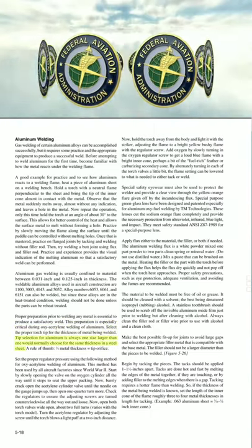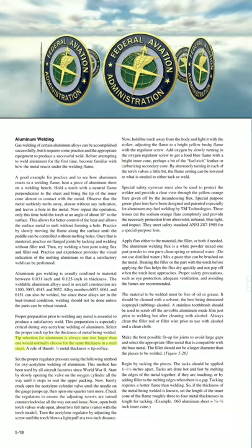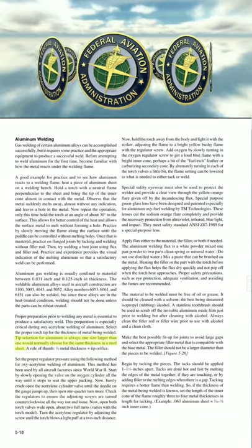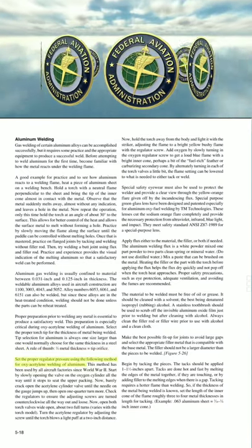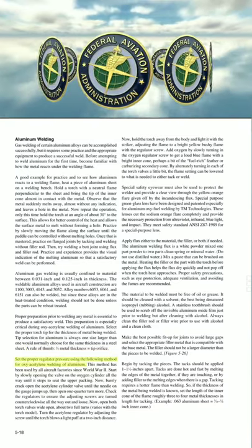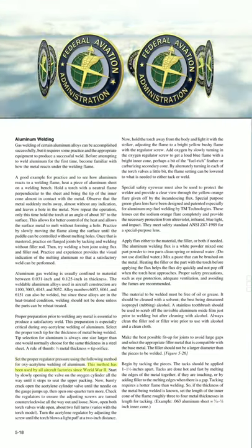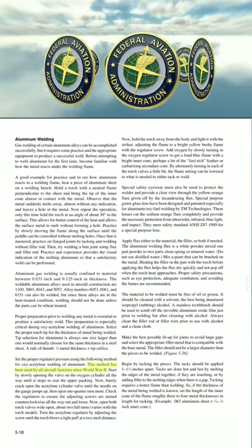Tip selection for aluminum is always one size larger than one would normally choose for the same thickness in a steel sheet. A rule of thumb: 1/4 metal thickness equals tip orifice. Set the proper regulator pressure using the following method for oxyacetylene welding of aluminum. This method has been used by all aircraft factories since World War II.